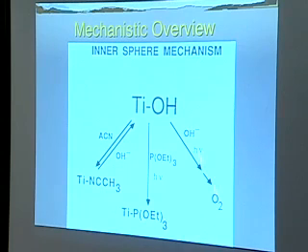And then finally, obviously, in the absence of those materials, hydroxide could bind, and you would go to oxygen. Well, we obviously know that when you electrolyze hydroxide, it does generate oxygen, so that path is correct. I will tell you that if you add a few millimolar of this phosphite into your solution, it is dead. You oxidize nothing at that point, and you can't just wash your electrode off with a little bit of water and restore it. The only way to get your nice single crystal TiO2 back as a photoelectrode is to polish it down. So that is binding, just like I said.